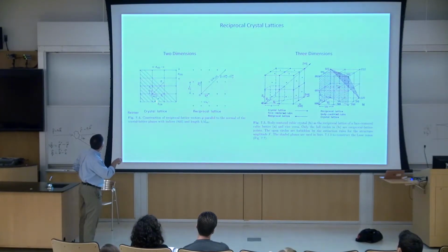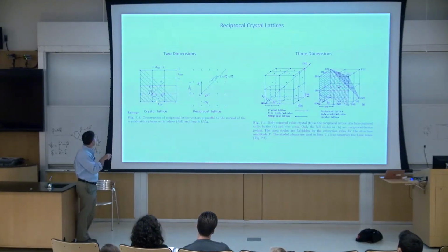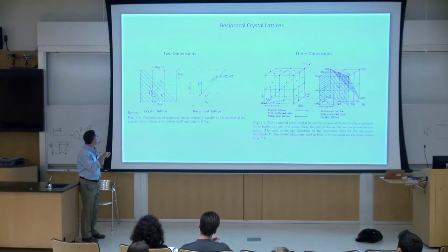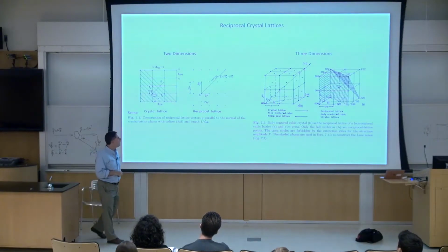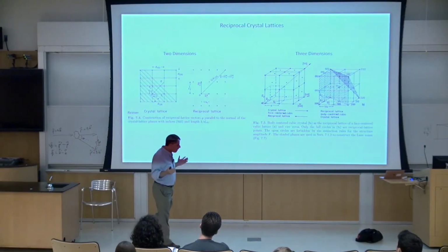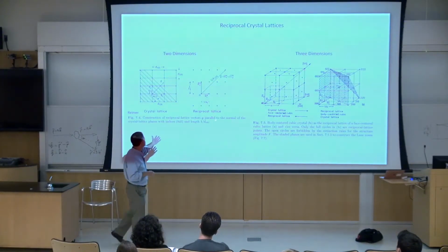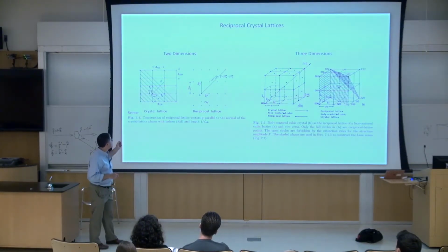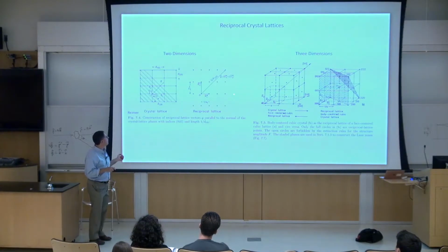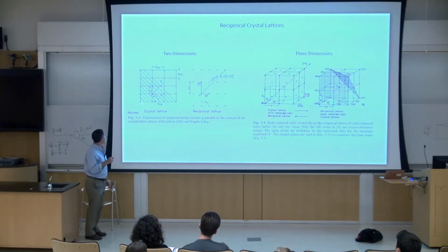No, this one is doing 1, 2, 3 times. So this one they've constructed a 320 spot. And you can see it's got lots and lots of lines inside the unit cell. So the fundamental frequency is like the 100 or something, it's the lowest order spot. And then when I start to see reciprocal lattice spots at higher and higher frequency, they're Fourier coefficients that are oscillating many, many times inside that unit cell.